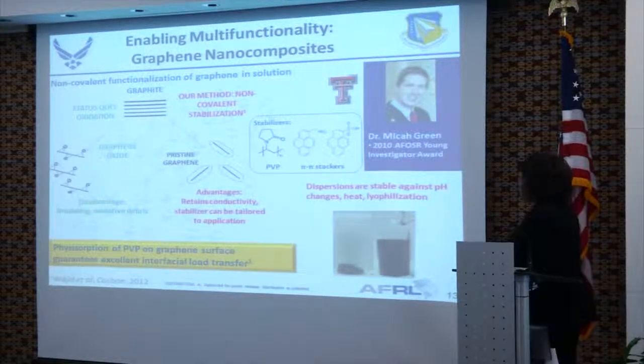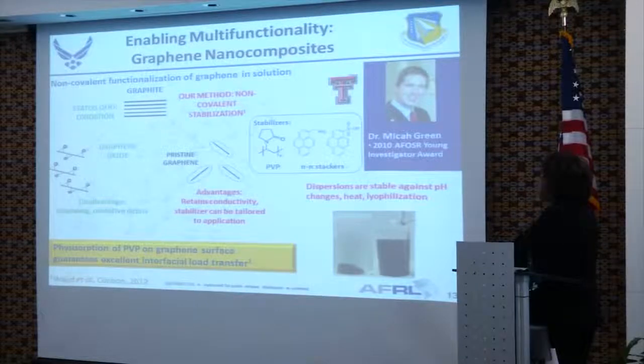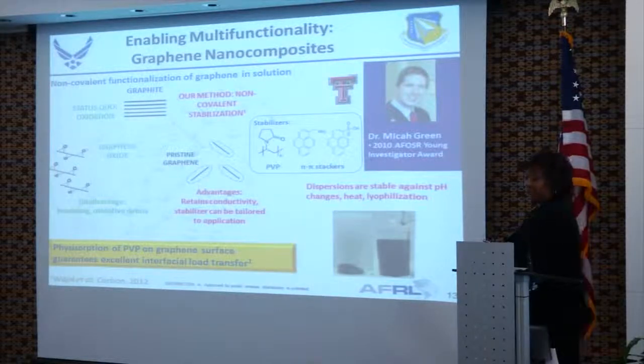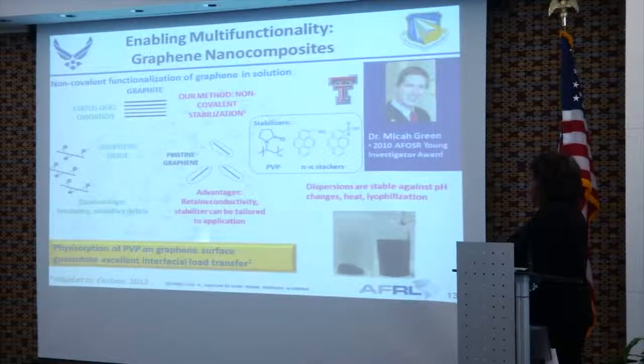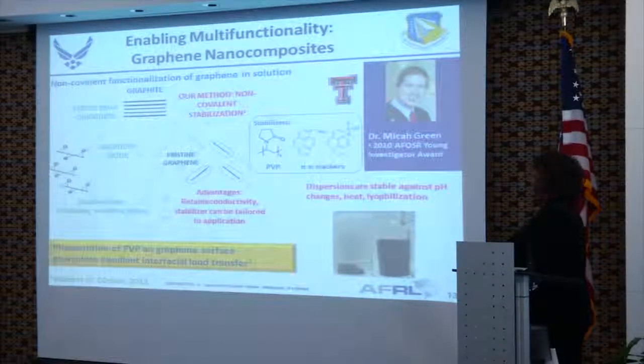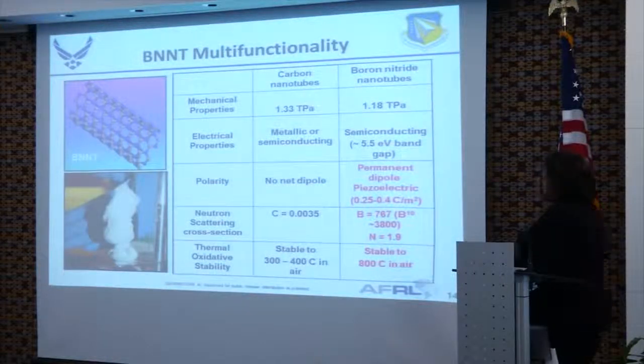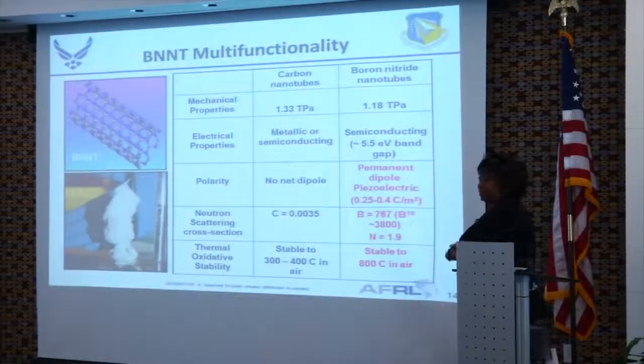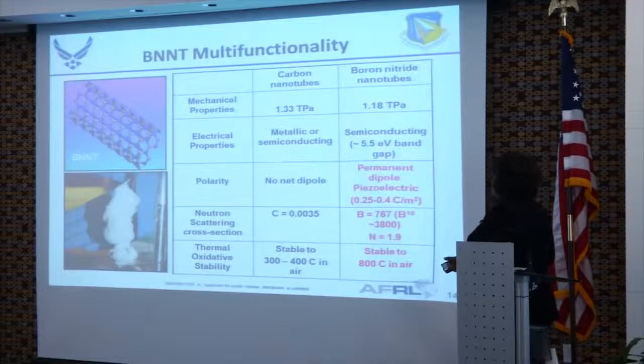And so he's been able to make very nice stable solutions of them. And if you can get that good physisorption of the stabilizers with the graphene, that should lead to good interfacial load transfer that we want to see with these types of materials. So moving along a little more quickly, I'd like to go back to another really favorite subject of mine, and that's boron nitride nanotubes.